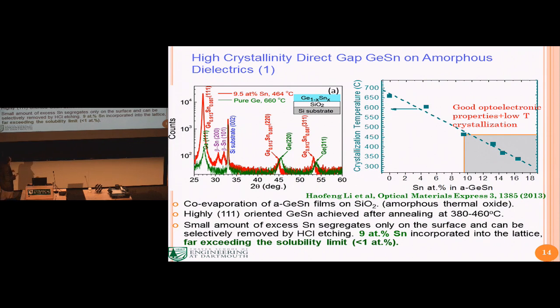Nothing will happen. So this crystallization process is really more like a phase transition in this sense. And after the crystallization annealing, if you're having a starting point of 9.5% tin, basically this is the X-ray diffraction pattern compared to the pure germanium. First thing you can realize is that there's an obvious peak shift. The peak shift to smaller angles is because you are incorporating bigger atoms of tin into the lattice. From that peak shift, you can actually derive that there's about 9% tin successfully incorporated into the germanium lattice.